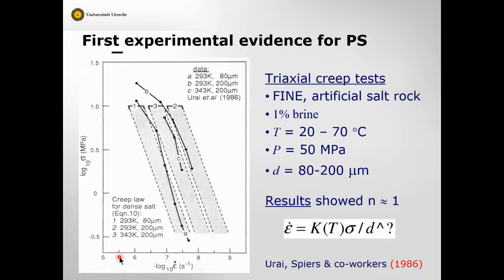This is log stress against minus log strain rate. So this is fast lab strain rates. This is slow lab strain rates. And these were samples with different grain size. This is very fine, deformed faster. This is a little coarser, deformed more slowly. What do you see here? The slope of this data, look, is 1 in this log stress, log strain rate plot. So that means there's a linear relation between stress and strain rate. So indeed, our results showed linear relation. The strain rate was linearly related to stress and definitely dependent on grain size, fine, coarse, same temperature, but